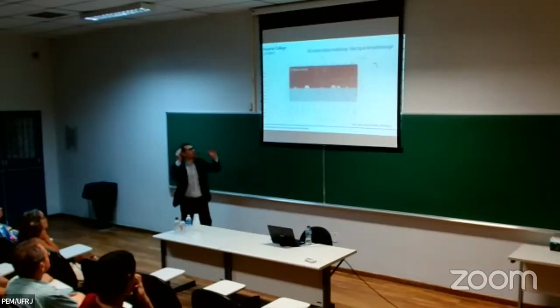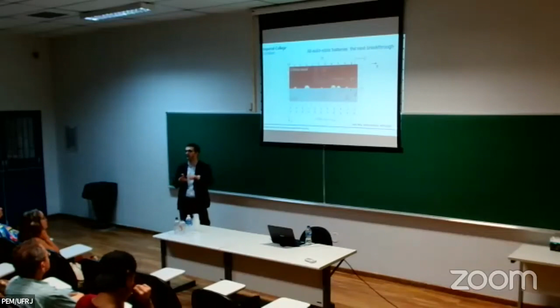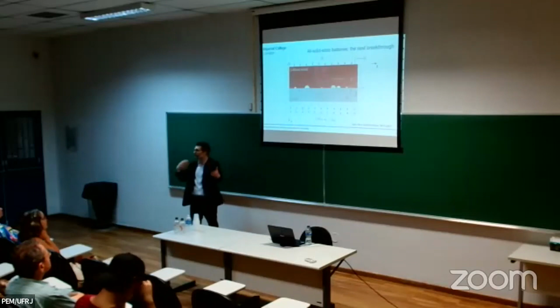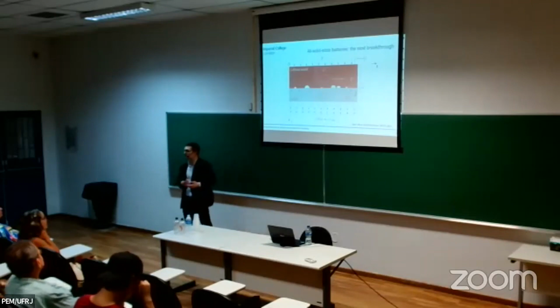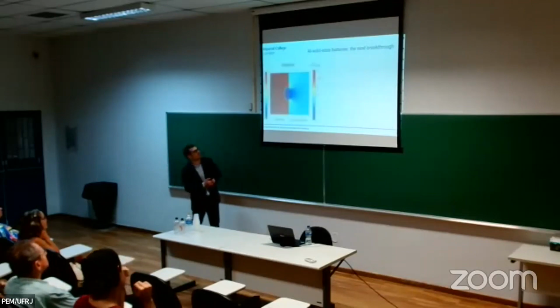You won't see maybe the equations here, but this is kind of the model that we have. So we solve an electromechanical problem. We have an equation for the lithium vacancy diffusion, we have an equation for the electrical field, we have a phase field equation that describes the evolution of those voids, and we have also all the creep and viscoplasticity. And these are the kind of results that we get.